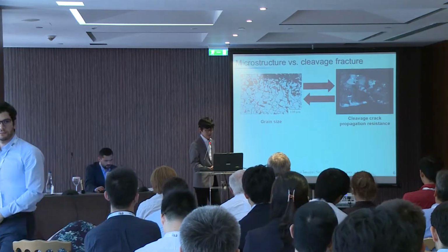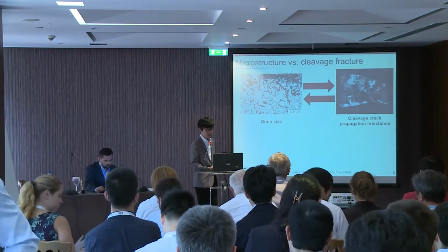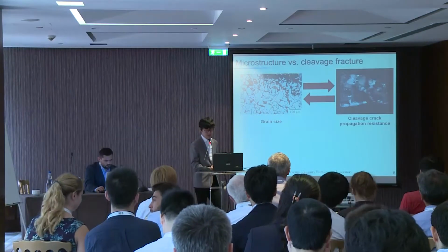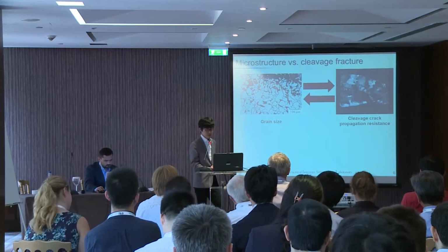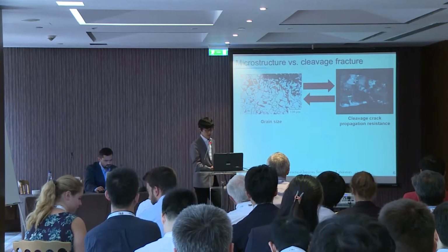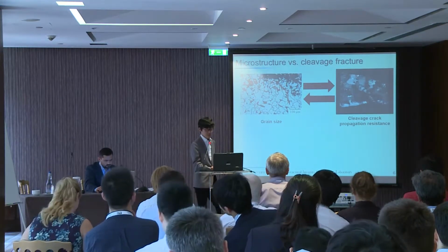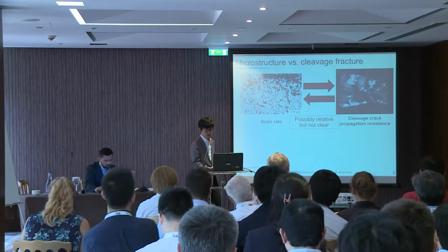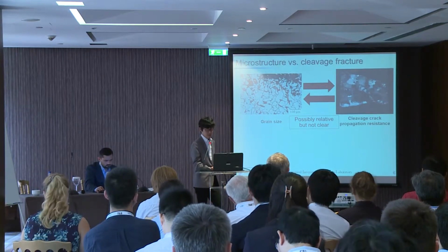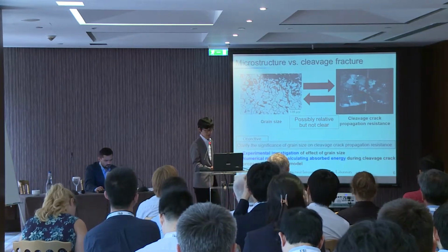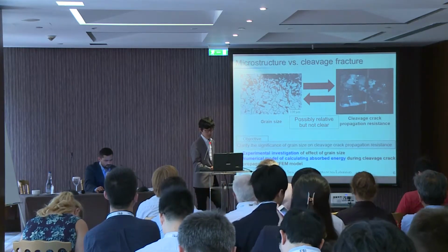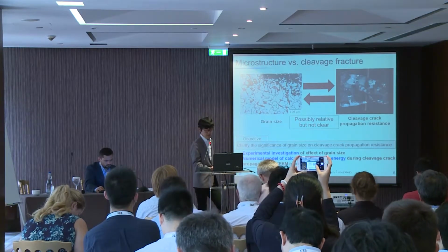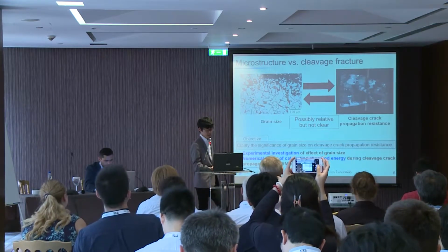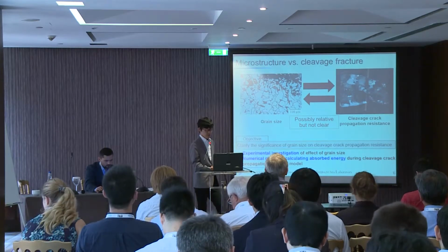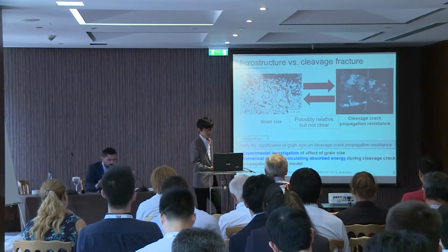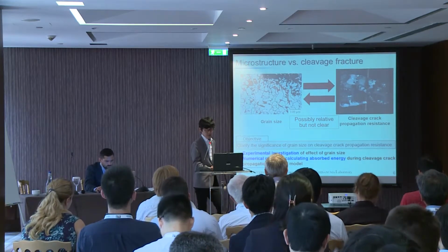It is well known that microstructures make a substantial contribution to material resistance to cleavage fracture. For example, the relation of grain size and brittle fracture initiation toughness is well known. However, the effect of grain size on cleavage crack propagation resistance is not clear, even though it is one of the most fundamental features of steels. So, our objective is to clarify the significance of grain size on cleavage crack propagation resistance. To do it, we investigated the effect of grain size experimentally and calculated absorbed energy during cleavage crack propagation by a numerical model using XFEM, presented by Shibanuma et al. in the previous session.